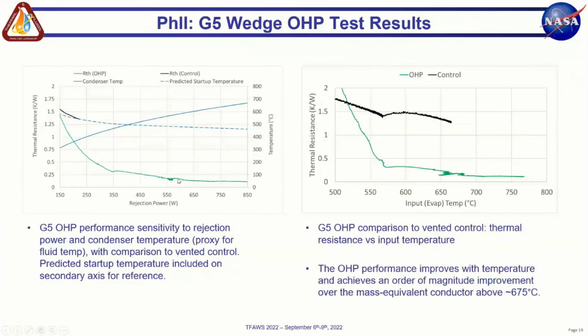Some more plots here comparing the thermal resistance to the rejection power. I don't have enough time to talk through these in detail, but one takeaway is that our predicted startup temperature is shown here in the dashed series, and where it intersects with this condenser temp is essentially our predicted startup temperature, with this prediction made before the test itself for this wedge. With your eye, you drop down to the thermal resistance. You can see this is a pretty reasonable startup prediction in terms of the evolution of the improvement in the part with power, matching the predicted startup temperature in QT space.